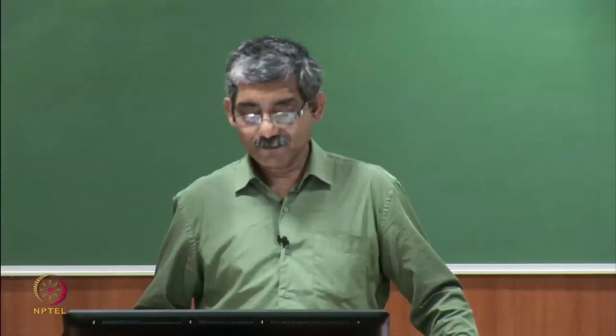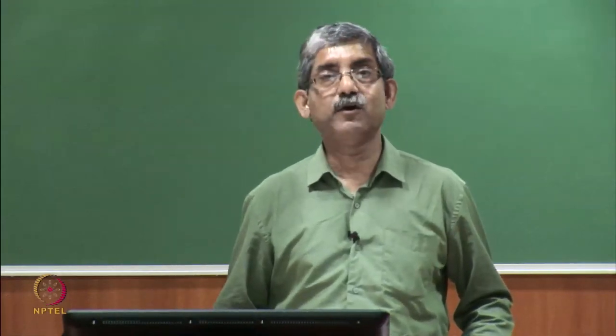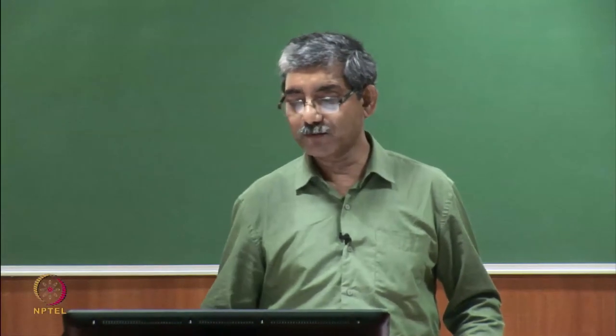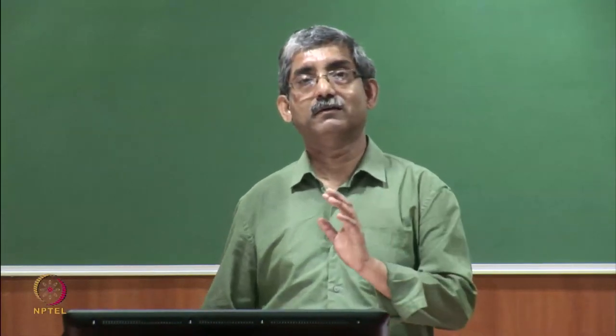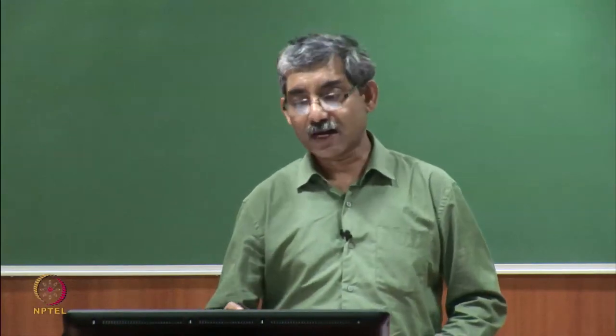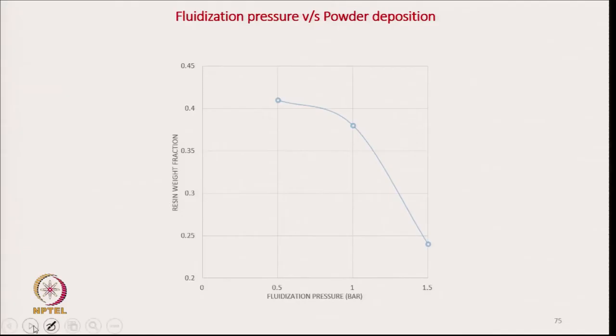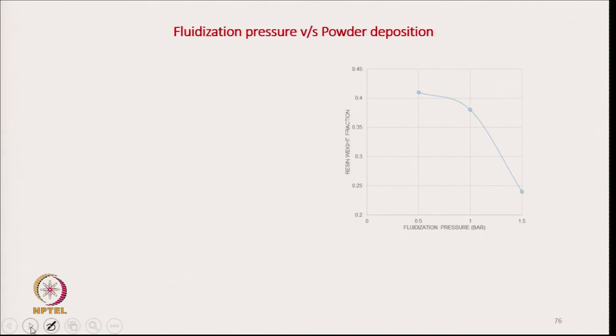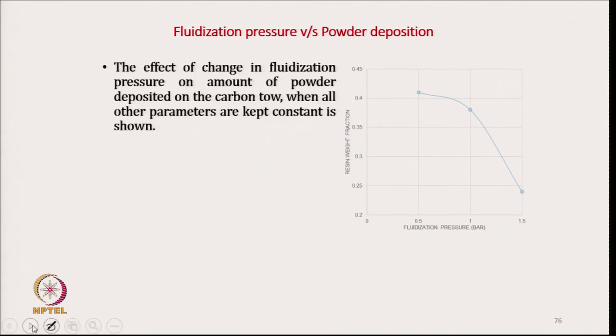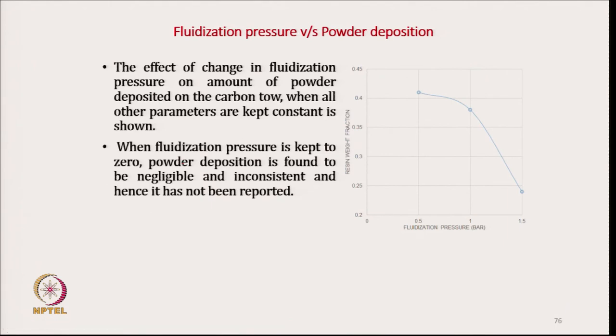Next is the fluidizing pressure. We have changed the fluidizing pressure from 0.5 bar to 1.5 bar, and the diagram shows that the resin fraction reduces consistently, initially at a lower rate and after that at a higher rate. Other parameters are kept constant. When the fluidizing pressure is 0, there is no powder generation, so powder deposition is negligible, and that is why we have not taken that part.